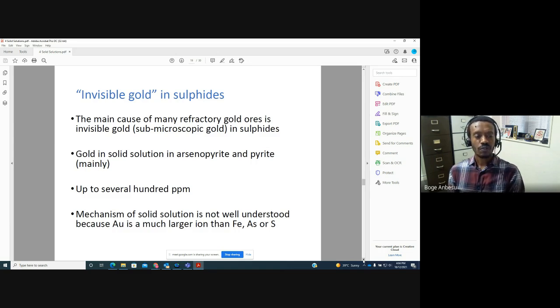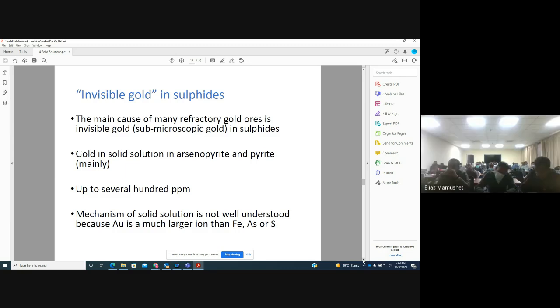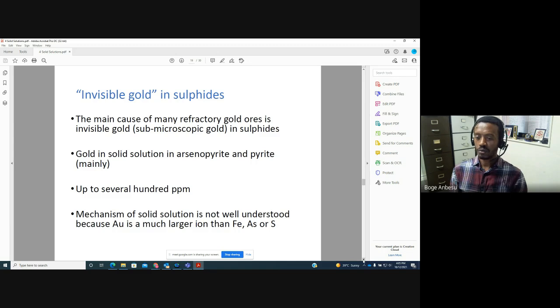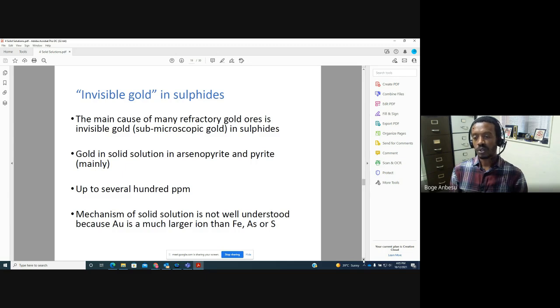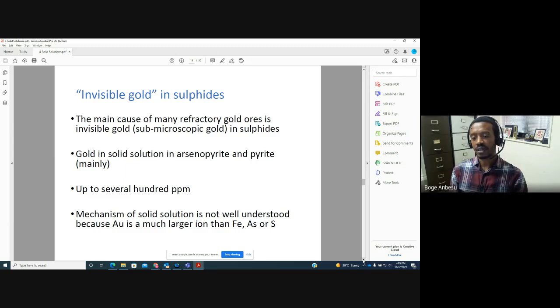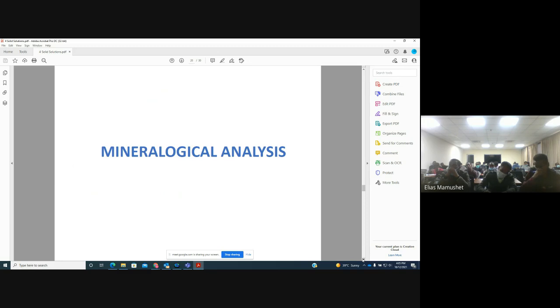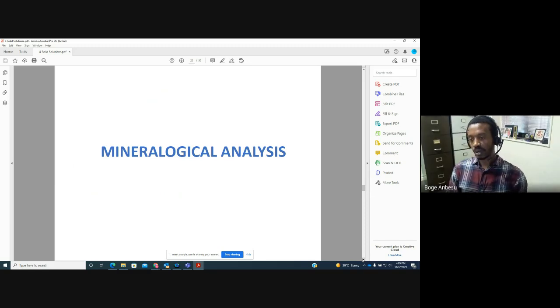Because, as I say, sometimes this can be economic and can be useful to extract the gold. In terms of how the gold is going into arsenopyrite, we actually don't have a full understanding because in arsenopyrite, we have iron, arsenic, and sulfur. Gold is not going to replace the iron because gold is too big. Gold is not going to replace the arsenic. It's too big. It's not going to replace the sulfur. Again, different properties and still too big anyway. So the only explanation is that gold is just sitting in the space as interstitial solid solution, rather than replacing any of the elements in arsenopyrite. So that's why we have interstitial solid solutions in gold ores, especially those containing arsenopyrite.